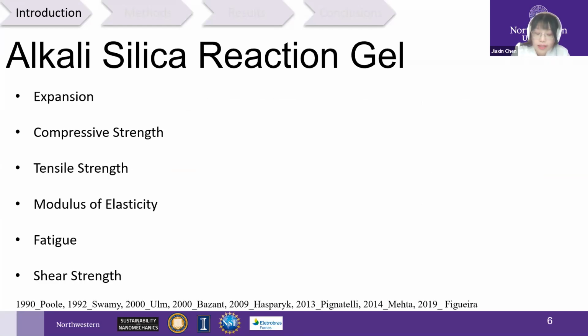Alkali-silica reaction gel causes cracks on the surface, but when the cracks get bigger and bigger, water and chemicals immerse inside the crack and will cause bigger problems. The long-term behavior of concrete structures may depend on various chemo-physical damage phenomena. Among them, the degradation induced by the alkali-silica reaction is of particular concern for the safety assessment of several concrete dams and bridges, particularly for those that were built decades ago. Many researchers have found that alkali-silica reaction gel expands, decreases the compressive strength of the concrete, decreases the tensile strength, modulus of elasticity, and fatigue performance, and even shear strength.